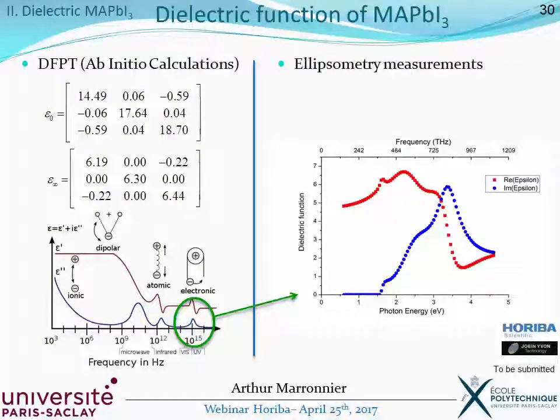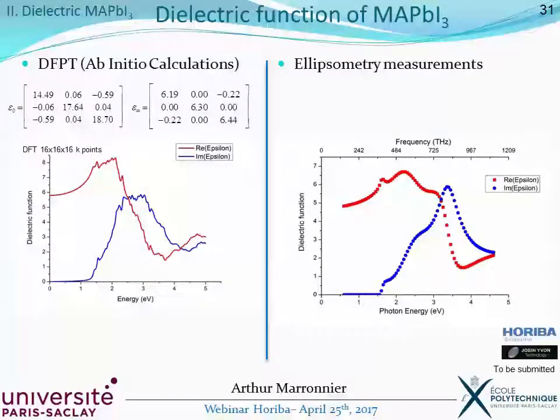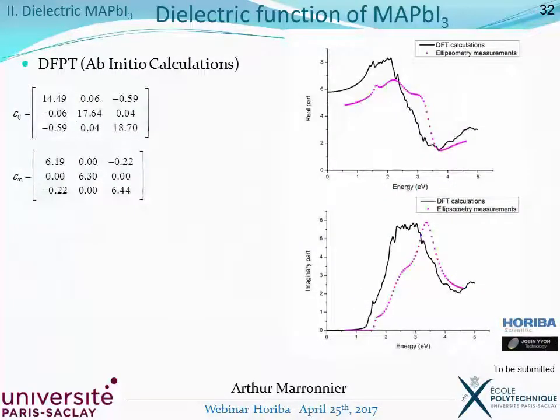Now, from the calculations, we can obtain a similar graphic to compare with this one. And here is what we have. So you can see again that you have globally a good match between calculations and experiments. If now we look separately here on top at the real part and on the bottom at the imaginary part, you see that you have a shift between calculations and measurement.